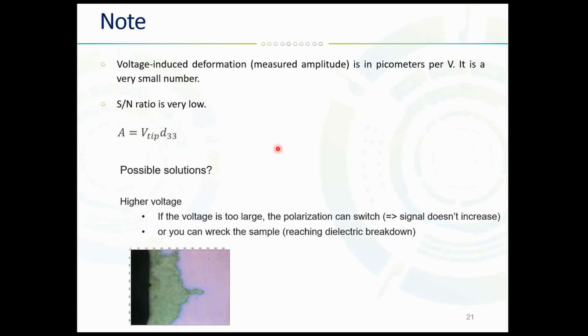Okay, but please note that the voltage induced deformation is quite small. It's picometers per volt, and it's a very small number. And this leads to a very small signal to noise ratio. And how can we solve this kind of situation? We can apply high voltage, but if you put too large a voltage, then you can basically burn the sample. And this is an example of the burned sample here.